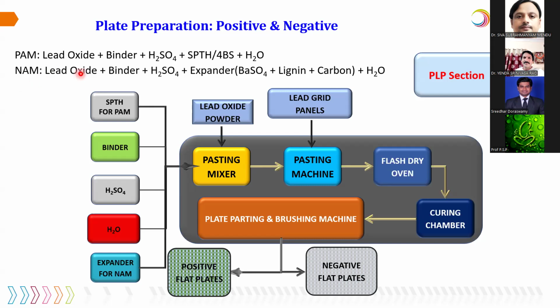Whereas in the NAM, lead oxide, binder and sulfuric acid are there, but the expander is one critical ingredient. This expander consists of 3 elements: barium sulfate, lignin, and carbon. These materials are added into the pasting mixer along with the lead oxide powder, where the lead grids or panels are pasted, and then go into the flash dryer and the curing chamber, where the conversion happens from lead oxide to tribasic or tetrabasic structures, and then positive flat plates and negative flat plates are made.